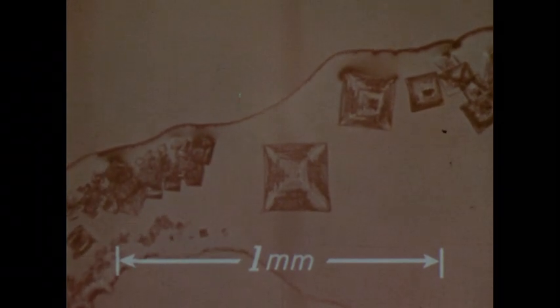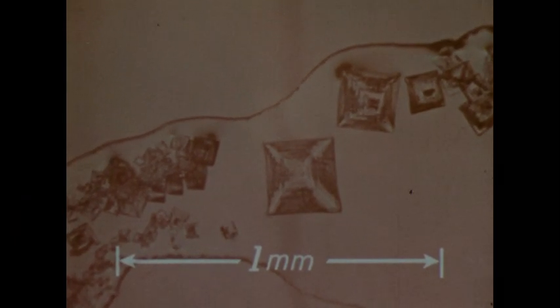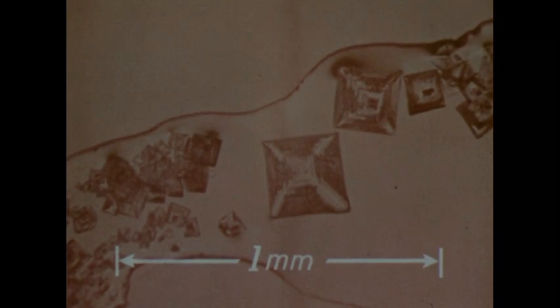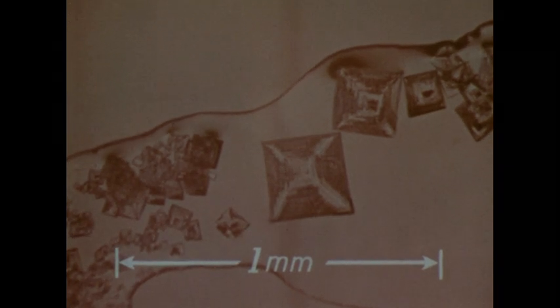During actual growth, these atoms are being packed together in a continuous three-dimensional structure whose front is progressing forward here at about 5/1000th of a millimeter per second. This means that orderly layers of atoms are being added to the crystal at the rate of about 10,000 layers per second. We cannot hope to illustrate this rate with the model. Although the model shows every atom lying quietly, we know that in the real crystal, each atom is vibrating a little around its average position because of thermal motion.